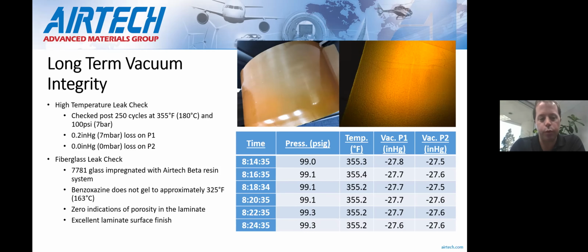So we wanted to have as broad of a window as possible where you might see any air getting entrapped in the laminate. Again, for those not familiar, that would look almost like a starburst of porosity coming through where a leak would be in the tool face. As you can see, a very clean laminate, a very high gloss as well, but zero indications of any porosity in the laminate and just an excellent surface finish.